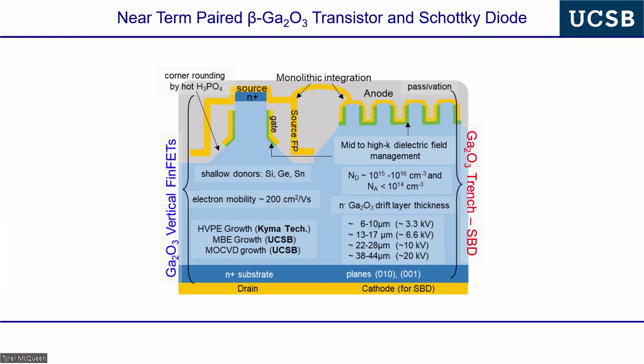The minimum requirement is that we have 3.3 kV Schottky diodes that are anti-parallel to something like a trench MOSFET, which is also rated at 3.3 kV. We're optimistic that with thicker epi, with controlled doping, we can go beyond what is commercially available in silicon or silicon carbide, approaching the record diode results in silicon carbide for blocking voltage. All of the pieces for this, except for these thick epi layers, are either demonstrated or in process.